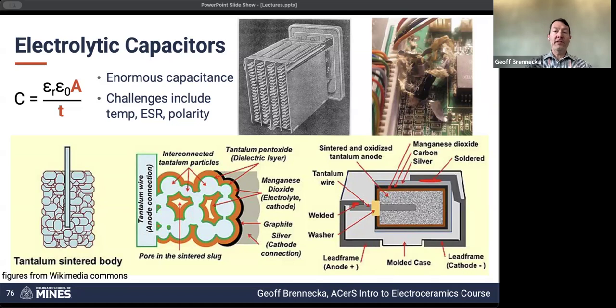The other part, if we're using this voltage, it's anodization, to drive an oxidation of the metallic layer, so we're turning aluminum into aluminum oxide, for example. If we turn that voltage around and operate it in the other direction, we can drive that reaction the other way. So we can start with aluminum oxide and reduce it to metallic aluminum. This is electrolysis. This is one way that we actually separate metallic aluminum from alumina ore to create metal, the metallic species. That's probably not what you want if you're trying to use this as a capacitor.